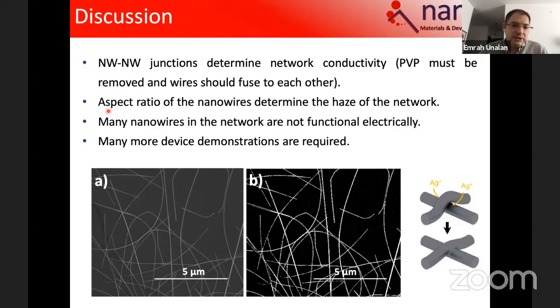The other issue, the second issue, is the aspect ratio. So the percolation states that the longer and the thinner they are, the less materials you need to put on to get the percolative network, right? So further studies should be conducted on improving the length and the diameter of the nanowire. So they need to be thin, but in that regard, the strain effect starts dominating.